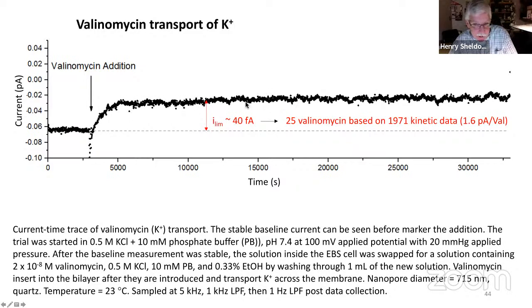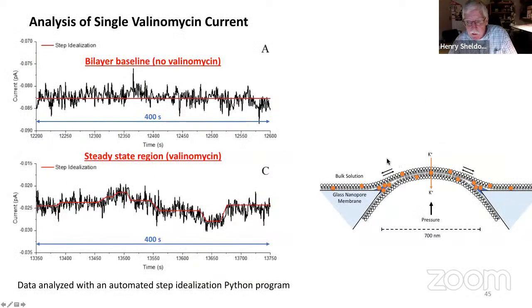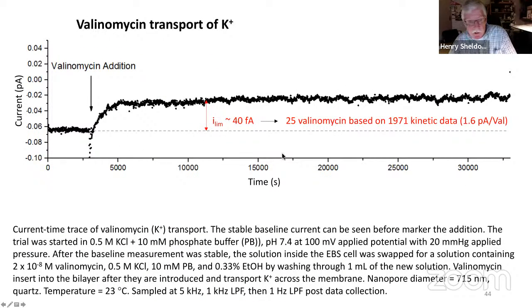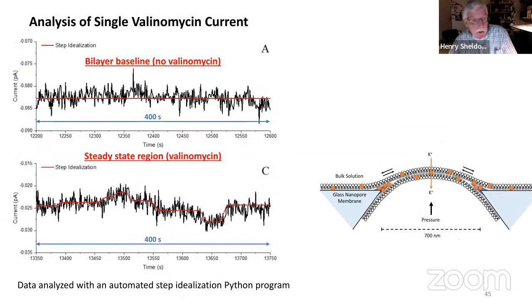The other thing you'll see about this, if you look closely, the noise over here before you put the valinomycin in is smaller than it is over here. You see a lot more structure after the valinomycin is in, a lot more structure in the current time trace, okay? And we believe that structure is a measure of the fluctuation in the number of valinomycins in the bilayer film. So here's a blow up. This measurement over here, 30,000 seconds, this is an 8-hour trace. All right, really long measurement. This is 400 seconds of the baseline current, and this is 400 seconds of the limiting current when the valinomycin is in the film. And you see there's more structure. It's noisy, but there's more structure in this current time response when you have the carrier molecule in the bilayer.